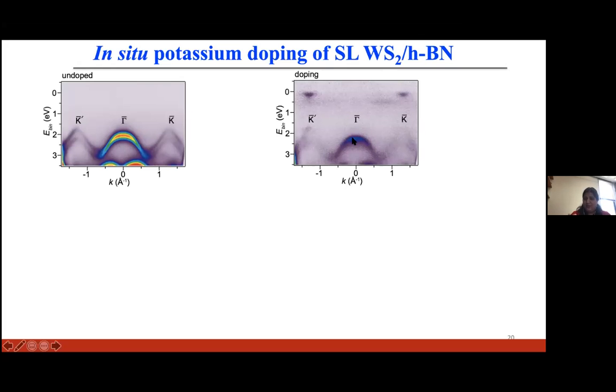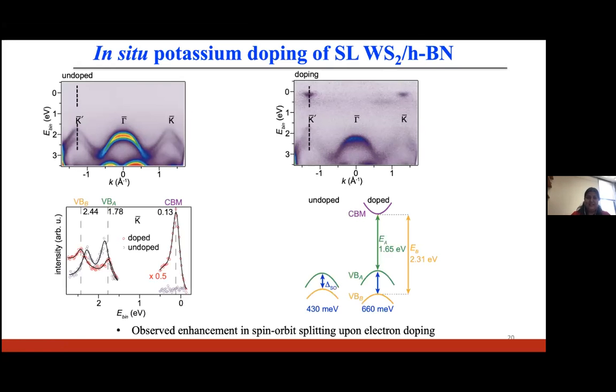In order to see what is happening, we can take line cuts, for the undoped sample and also at the highest doping, which I'm showing in this graph. We see a very interesting thing. The splitting in the valence band for the undoped sample is about 430 meV. But at the highest potassium doping, the splitting actually increases, from 430 meV to about 660 meV. We also observe that the band gap decreases. It was interesting because the spin-orbit splitting is increasing just by electron doping.